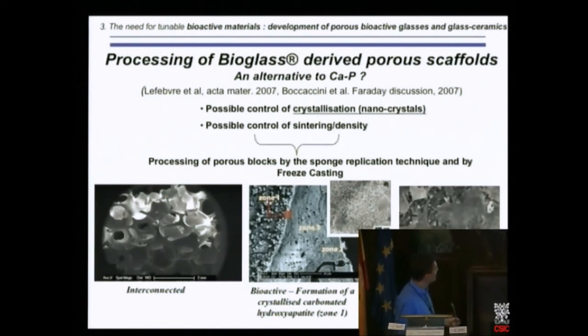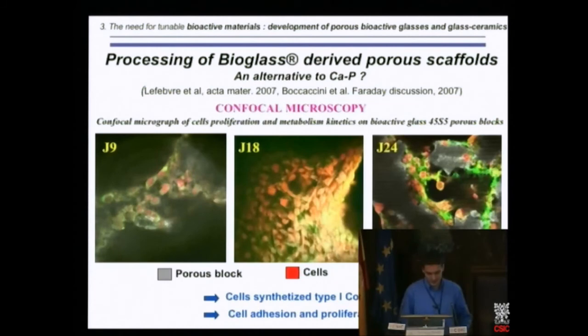So here are some images of a porous bioglass scaffold. Here is the image at higher magnification of this scaffold, the strut, after a given amount of time in simulated body fluid. After a certain amount of time in body fluid, we can see some carbonated hydroxyapatite at the surface, the same type of hydroxyapatite that we have in the body. So these are really nice, very small nanocrystals of carbonated apatite. And what is important is that we need to check that the osteoblasts, the real cells, adhere and proliferate on the surface and through the porous blocks. And that was really the case.